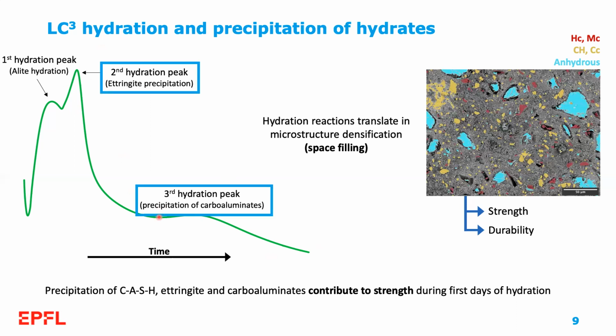In this presentation, I will focus my attention on the second hydration peak linked to ettringite precipitation and the third hydration peak, which is associated with the precipitation of carboaluminates.